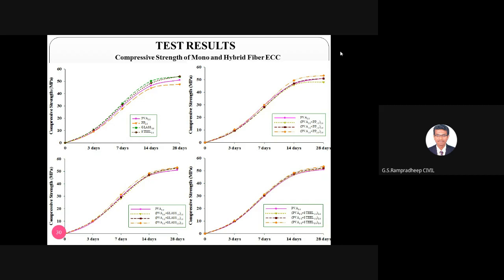And I will point to one result which is the very best result, PVA plus glass, because they are adding a larger volume of the glass material, right? 2/3, around 65%, and PVA around 1/3, 33%. We obviously know that 2200 MPa will be the tensile strength. So the brown color diamond is increasing to almost around 50 MPa. The target strength is achieved for M30, right?